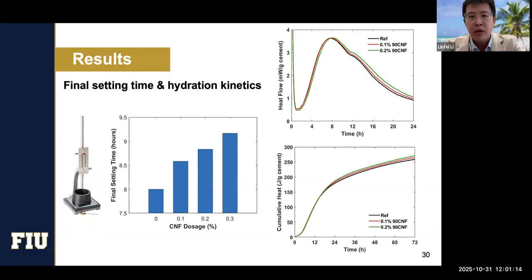We did some hydration kinetics as well, which is still ongoing, so we only have results from 0.1 and 0.2%. As you can see, there's not much difference, but there is a slight delay from adding the cellulose nanofibril. I think there's a debate on that. A lot of people talk about the nucleation effect, where you can accelerate the hydration process, but on the other side, the nanoparticles are going to stick on the surface of the cement particles.